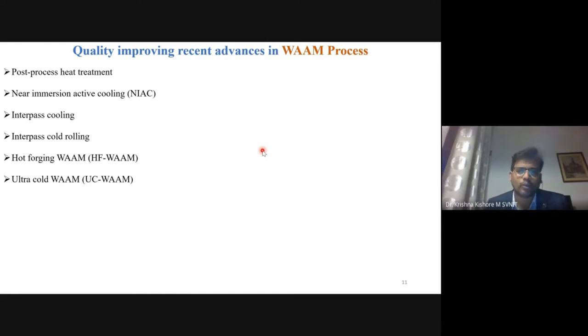To control this and normalize it, we generally do a post heat treatment process. We also have strategies like interpass cooling. That means we deposit a layer and hold for some time so that the temperature reduces to a certain interpass temperature, depending on the material. Then we deposit the next layer. If we are not able to allow it to cool for some time, people use different gases in addition. They place some gases in between and allow it to cool faster. People are also doing interpass rolling, like hot forging or cold forging. They deposit one layer, let the roller pass over it, compress the layer, and then deposit another layer. These kinds of strategies can be used for the improvement of quality.